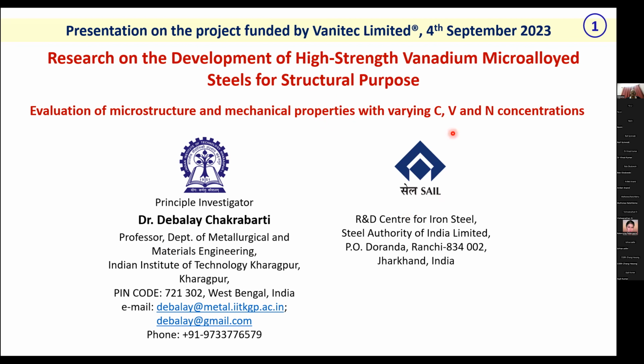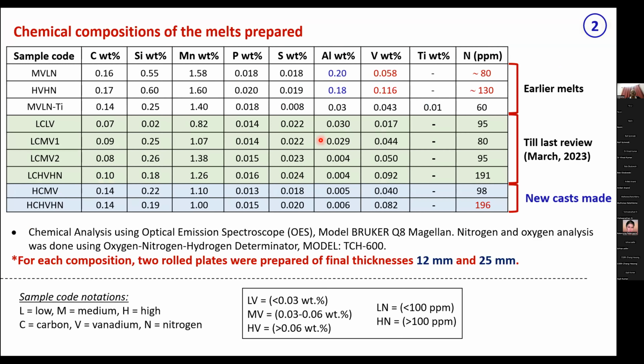So we studied the effect of composition, primarily carbon, vanadium, and nitrogen, and how far we can reach. Because now I think they are making up to 350 grade, which we want to enhance. So what we have done with this background, so the required properties are tensile properties, and impact toughness is a very important property, because nowadays in India also steel is being used in cold terrain, where a good impact property at low temperature is important. And we know that niobium has several issues for which vanadium is preferred.